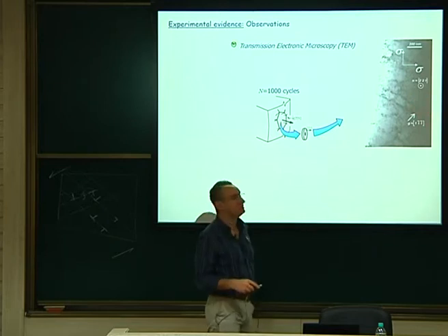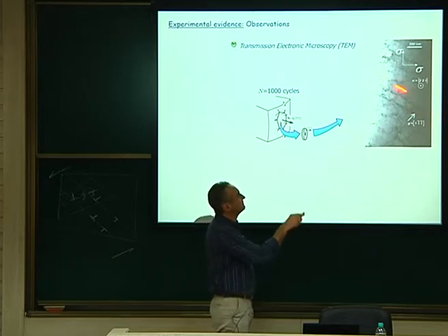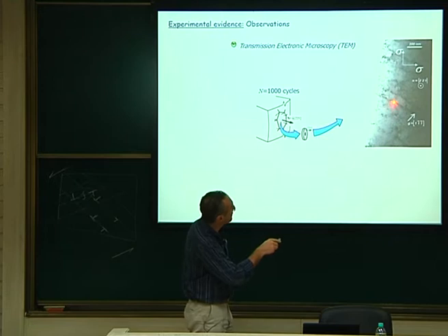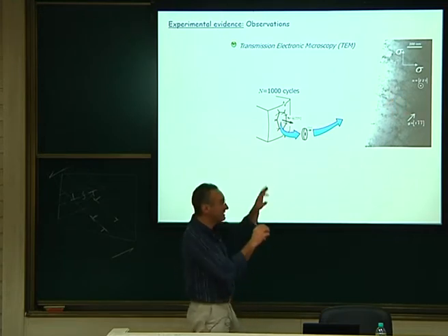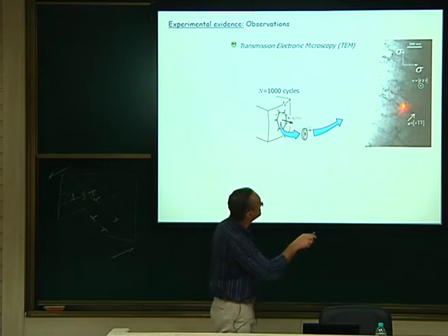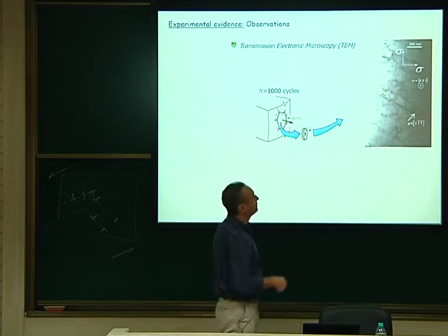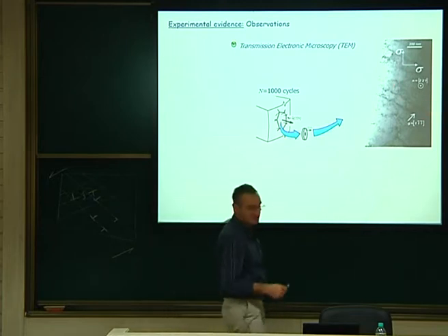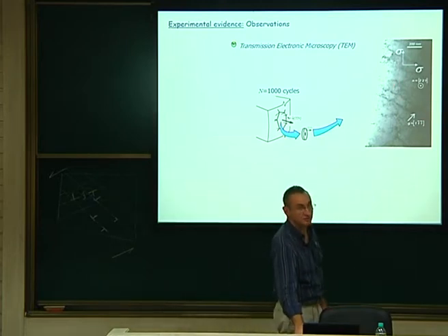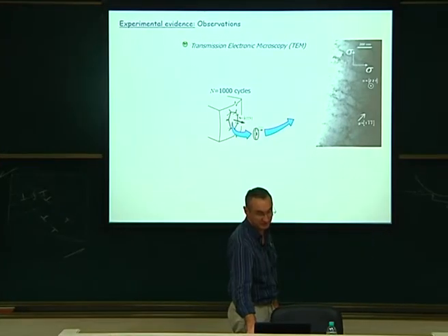This is typical of fatigue. This is called a persistent slip band, and you have this here, which looks like what they call a ladder-like structure. You see, it looks like a ladder you are climbing on. You see you have your ladder structure with the bands here. This is typically a persistent slip band formed in that specimen. So it means that the loading condition corresponds to fatigue, indeed.